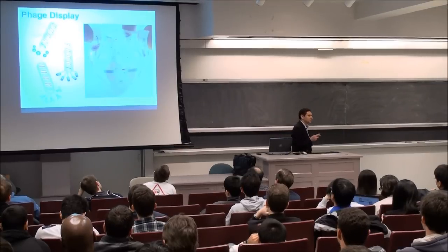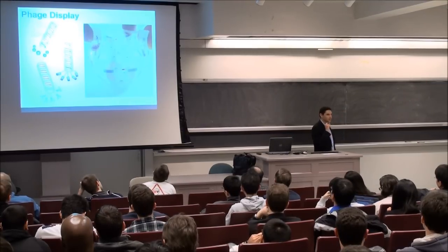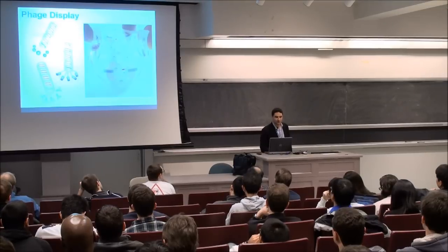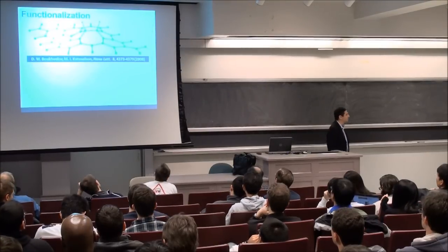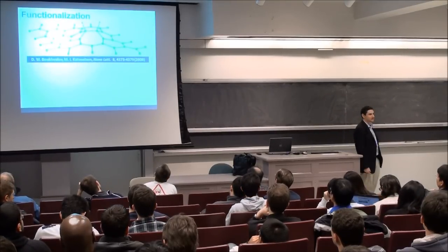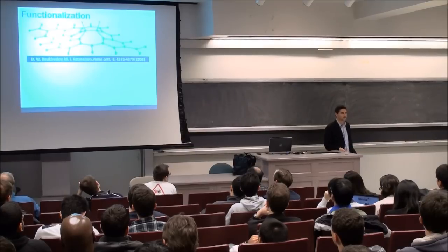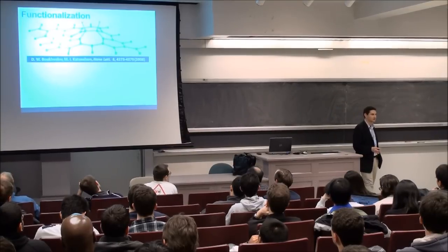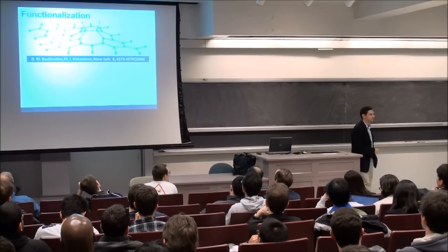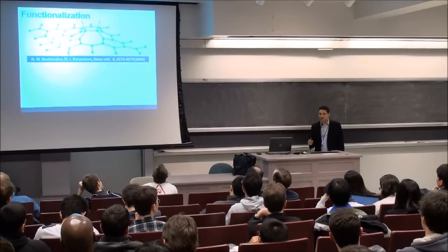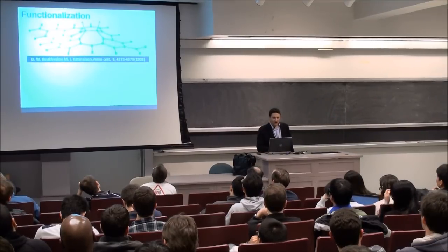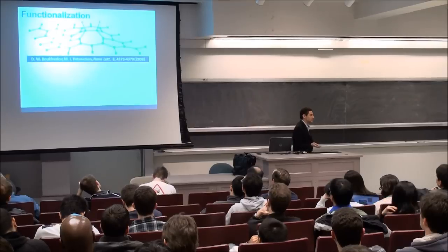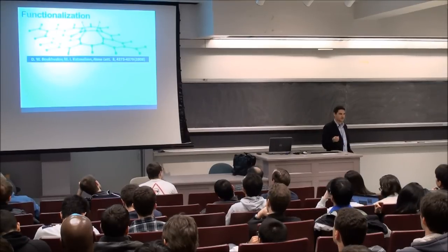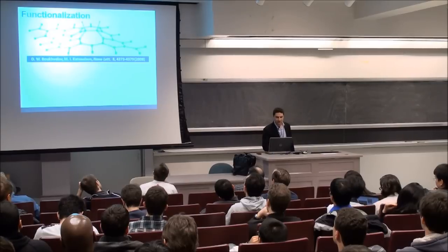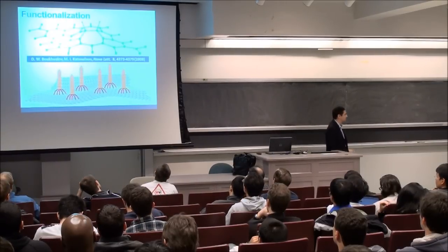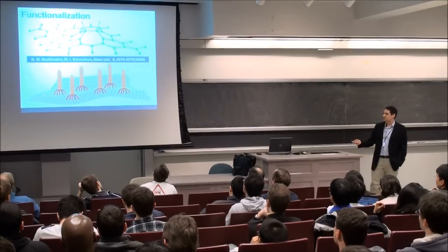So the problem with graphene is you don't necessarily want to covalently modify the graphene, because if you do, you're actually going to have to break the bonds in the graphene to do that. And that's going to actually lead to changes in the graphene properties. For example, the electronic properties, which we don't necessarily want to modify. We want to keep them so that we can keep that single bacterial resolution. So this phage display is a perfect approach for this, because you can generate peptide sequences that non-covalently bind to the graphene.